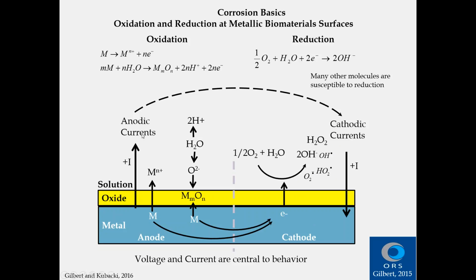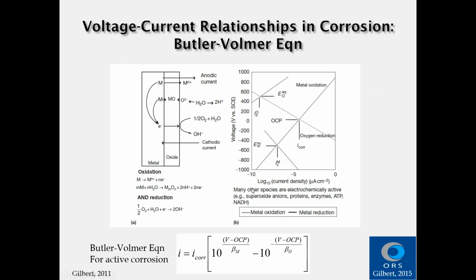But you'll notice that the positive ions create a positive current out into the solution, and then the cathodic currents create an equal and opposite current. And so while there are currents flowing, typically without an external source, these all happen on the single implant surface. And again, when you think about this in the context of currents, the metal is oxidizing, the oxygen is reducing, and because they have to balance out on average, you wind up at a curve that defines the corrosion current and the open circuit potential for that system, where these two lines that intersect at this point are given